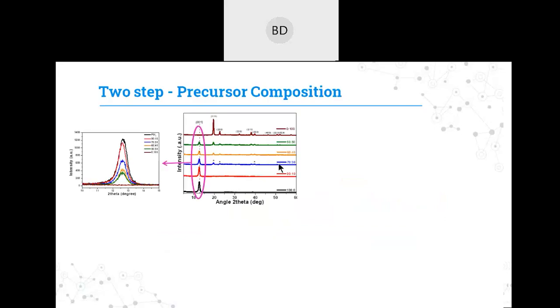What this lead nitrate is doing in this film is, if you see the diffraction patterns here, the crystallinity of the lead iodide which has formed by using these precursor compositions has been decreasing with increase in the precursor compositions. This decrease in the crystallinity shows that the PbI2 morphology is loosening up. It is creating some more space so that the MAI can be intercalated in the structure and a better perovskite can be formed in this case.